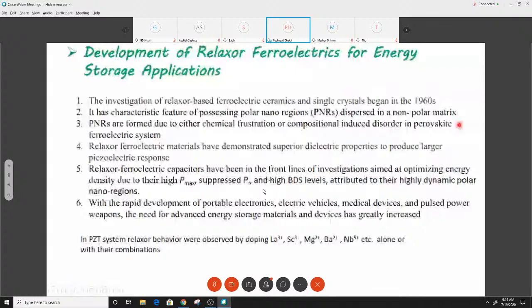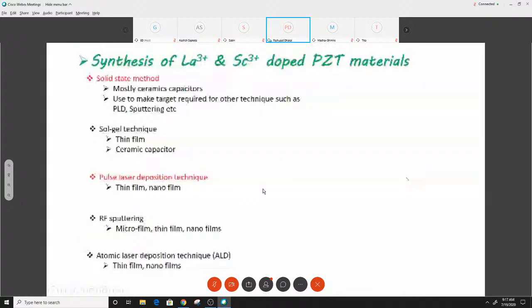In the relaxor ferroelectric capacitor, it has a high maximum polarization with suppressed remnant polarization and high breakdown strength, and that attributes to the high energy density of the capacitor. In the PZT system, the relaxor behavior can be enhanced by doping lanthanum, scandium, magnesium, barium, niobium, etc., alone or in combination. Here I am going to discuss the synthesis of lanthanum and scandium substituted PZT material by the solid state method and pulsed laser deposition technique.